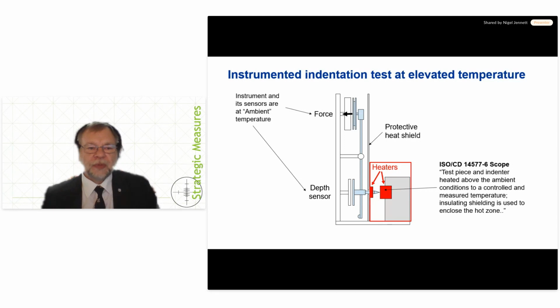European Metrology Research Programme called T3D, which specifically looked at what we needed to do in order to put in place a new standard for elevated temperature instrumented indentation testing. So there is a draft. It's called a committee draft, that's the CD. So ISO CD 14577 part 6. The scope is for instrumented indentation testing at elevated temperature, and that is defined as a machine where the test piece and the indenter are heated above ambient conditions to a controlled and measured temperature. And insulating shielding is used to enclose the hot zone so that the instrument and sensors are at ambient temperature. So that's distinct from operating the entire device in a furnace, which is not covered by the standard.